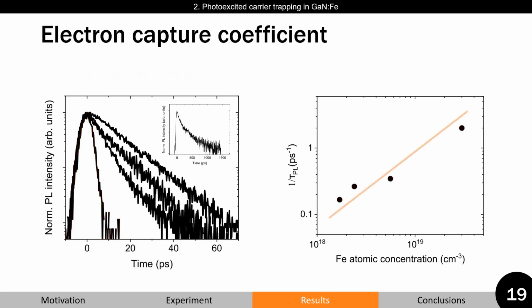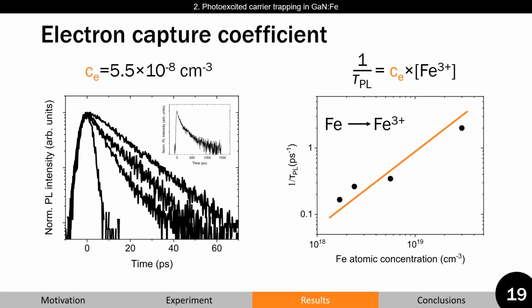We know that in our studied samples, the dominant impurity is iron, and in current experimental conditions, iron is predominantly in its 3+ state, which acts as an efficient electron trap. Therefore, we can attribute the drastic changes in photoluminescence to electron trapping and evaluate the electron capture coefficient.